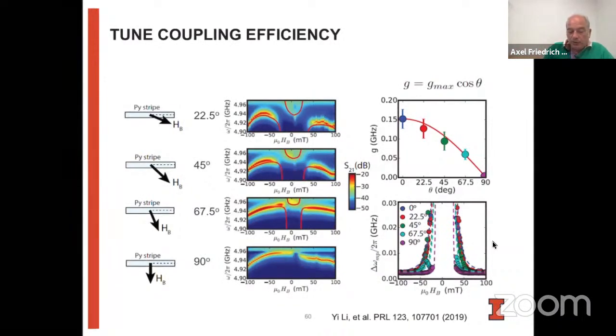So as we rotate the field around, we expect the coupling to decrease. And indeed, that's what we see. You see, as the angle becomes larger, this gap between the two modes vanishes until it goes completely away at 90 degrees. Now we see still a little gap here in the center.